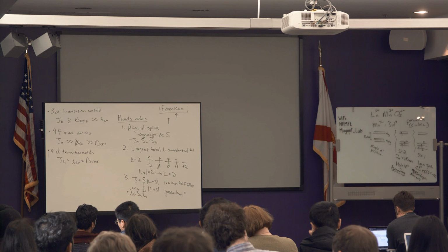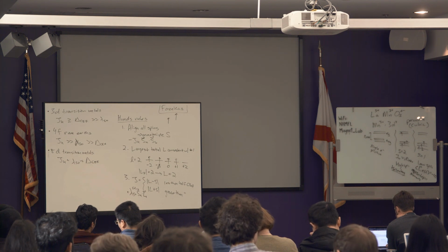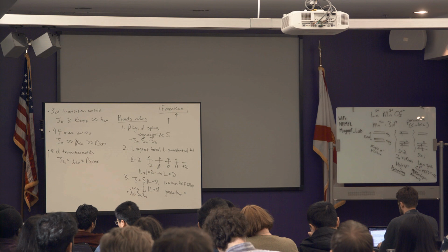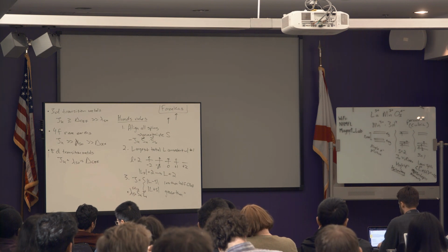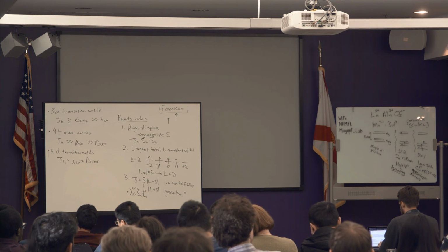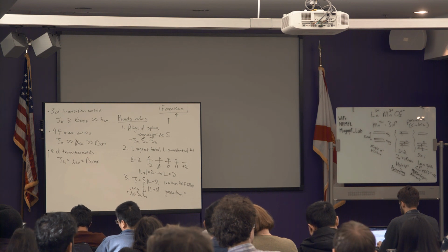And then you can look up, it's tabulated for all of these, what the possible crystal field configurations are. So in this trigonal case, we get 2 doublets and 5 singlets. Singlets are going to be totally non-magnetic, and then praseodymium will be very boring as long as you're at sufficient temperatures below your crystal field splitting.